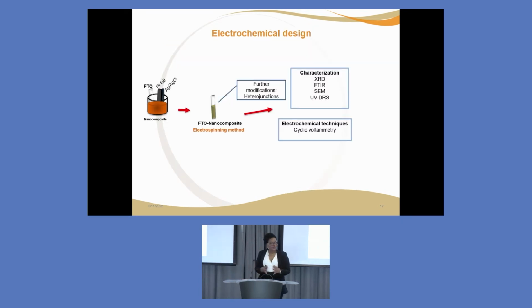Now, when it comes to the design of our electrode, we normally use FTO, which is fluorine-doped tin oxide electrode, and we electro spin. So that means that we take our nanocomposite and drop cast it on the glass, spin it, and keep it to dry for some time. When the electrode is dry, we use it for electrochemical activities.